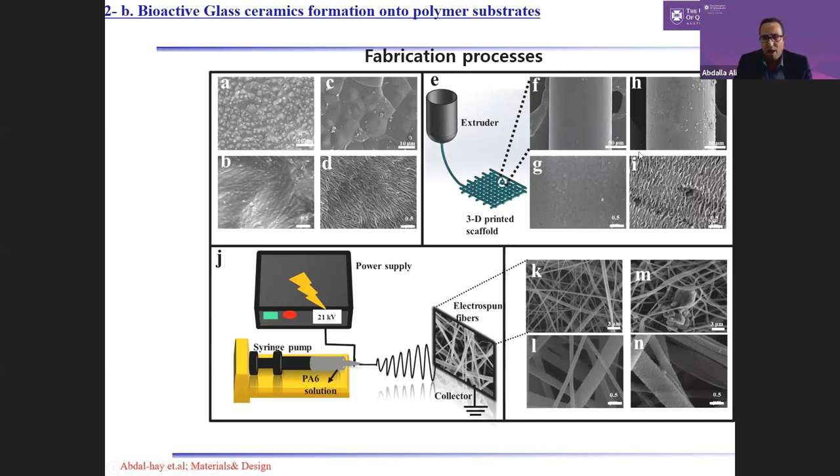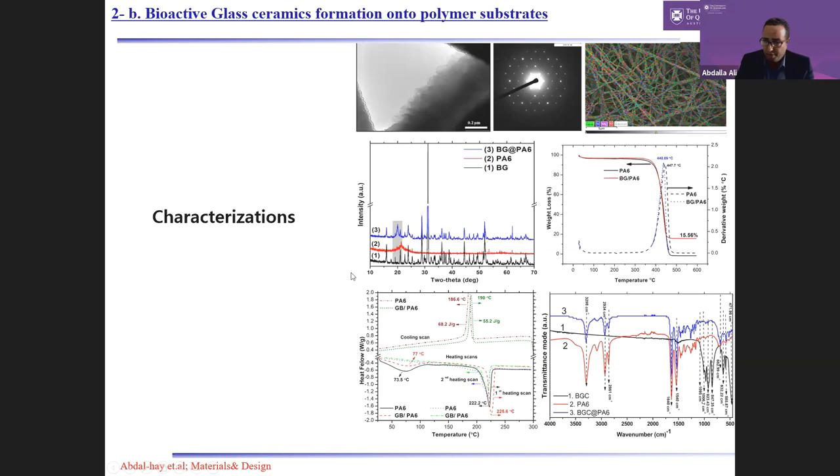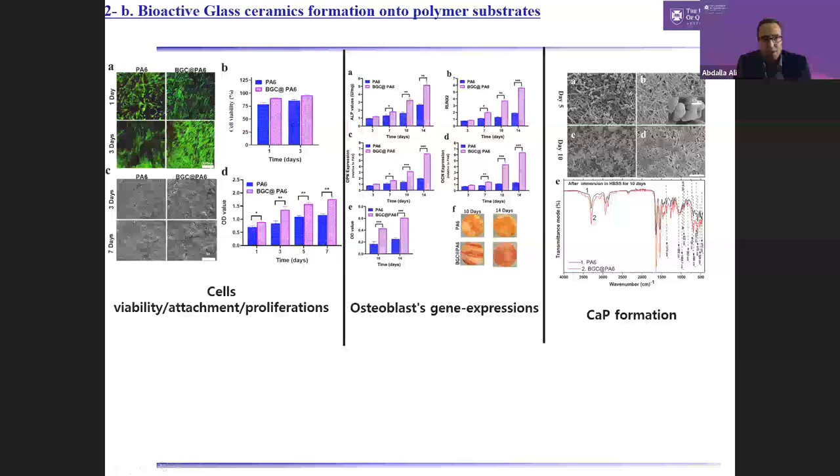We also tested this hypothesis using a 3D printer and electrospun fiber. Then we characterized the surface to prove the precipitation and the formation of bioactive glass on the surface. We also did viability of osteoblast cells on the surface, and showed how bioactive glass on the surface accelerates early bone formation, and as well, after the precipitation of bioactive glass on the surface, we tested the mineralization functions